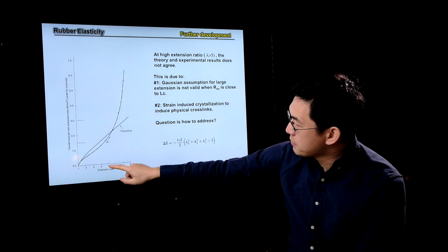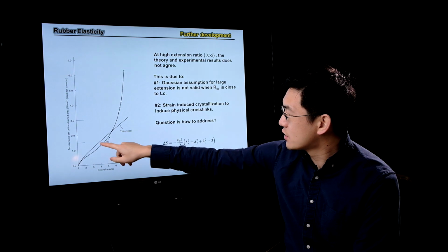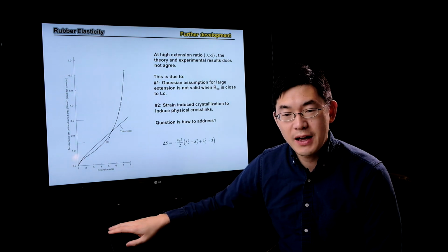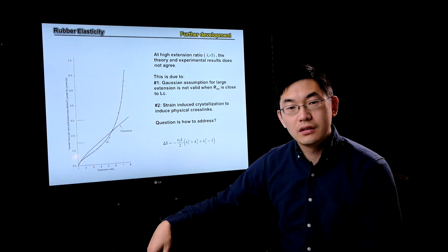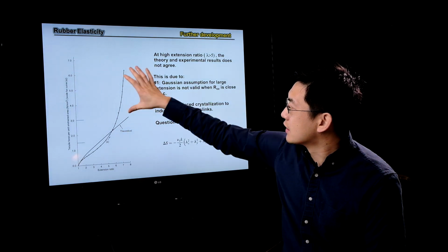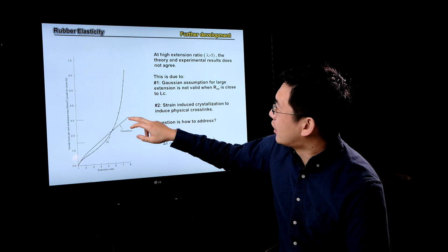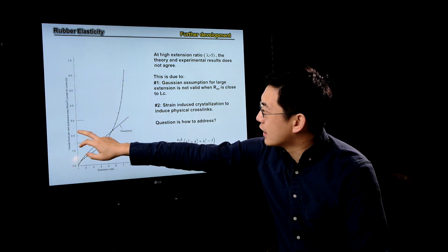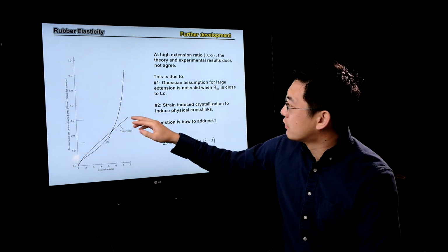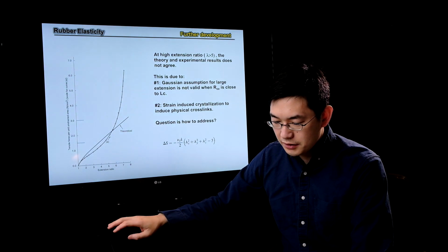I would say between 1 and 5 degree of strain, it's pretty much similar. There is some deviation, but not terribly bad. But once your strain is above 5, your rubber elasticity deviates dramatically from what the theory predicts. It can be up to 100% difference: the theory predicts the force per unit area will be about 3.0, while the reality people measured is already exceeding 6. That's a big difference.